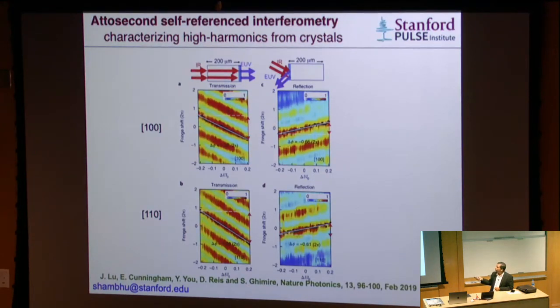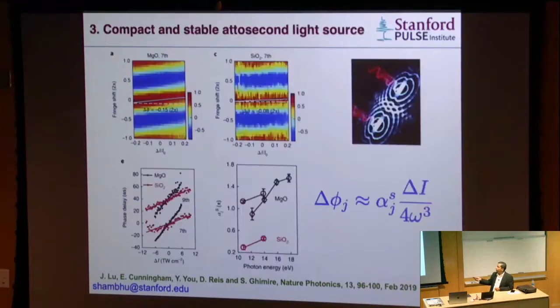The reason why this moves down by so much is because of this propagation effect that is occurring in the crystal. So there is a paper that talks about this in much more detail. What I will tell you today on this is just that we use the same platform to study how this fluctuation depends on the different materials. Okay, the fluctuation meaning the shift of the harmonic photon energy as a function of relative laser intensity, how that depends on certain source materials. Okay, so here we compared magnesium oxide and quartz. And we find that in magnesium oxide, the fluctuation is much bigger than in quartz. Actually, consistent with the MPQ experiment, they use quartz, and we also find much smaller deviations in quartz compared to magnesium oxide.